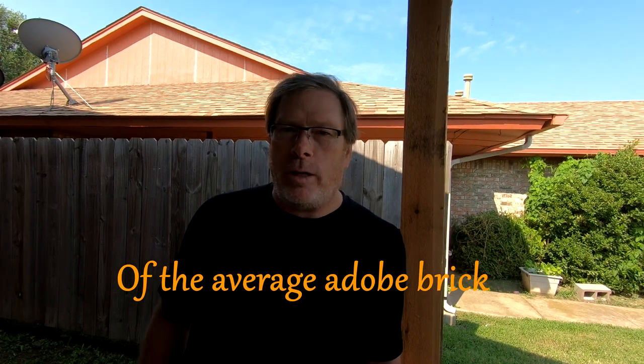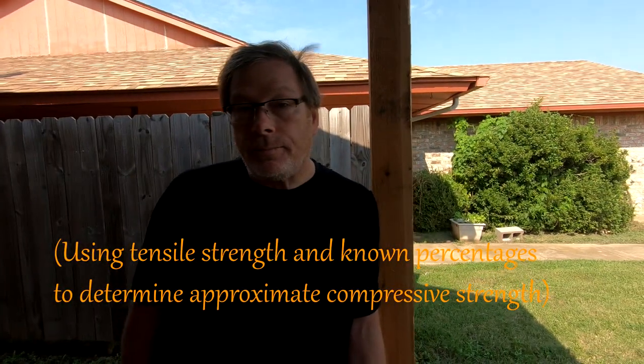Now, its tensile strength is between 10 and 20% of its compressive strength. So if we go backward on that, the compressive strength is between 5 and 10 times the tensile strength. So if this is 0.6 megapascal, and we multiply that by 5 and by 10, we might assume that the compressive strength of the brick would be somewhere between 3 megapascals and 6 megapascals, which is much more than we need. We only need about 2 megapascals. So this is a good indicator of where we may be in compressive strength, but we still need to do a compressive strength test to be sure.